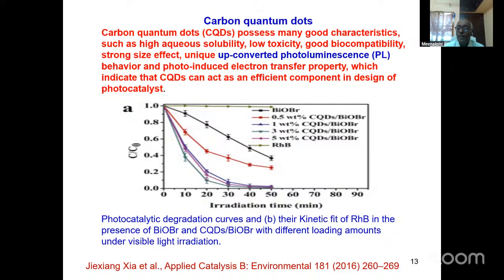Actually, one of the unique properties of the carbon quantum dot is upconversion fluorescence. When you irradiate an organic molecule or any fluorescent molecule, what will happen is, if you irradiate with 300 nanometers, you will get the emission at 400 or 500 nanometers. That is a redshifted emission. Whereas in the case of carbon quantum dots, depending on the excitation wavelength, you may get different emissions. So that is the specialty of the carbon quantum dot.